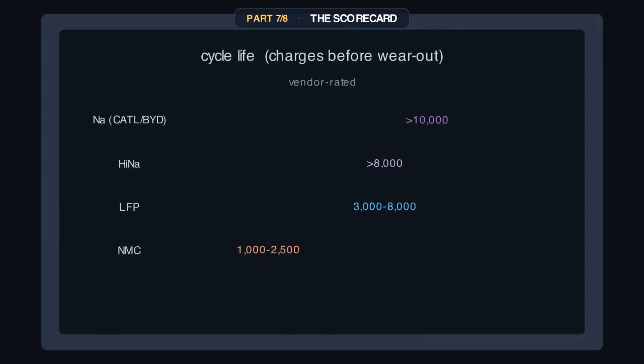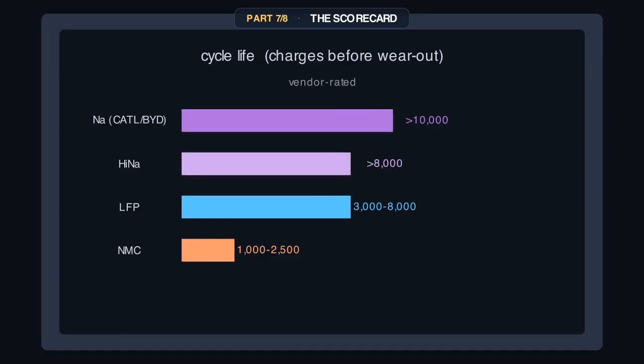Here the challenger lands a real punch: cycle life. Manufacturers rate the best sodium cells above 10,000 charges. CATL and BYD claim past 10,000. HiNa past 8,000. I'll attribute those to the vendors, but even conservatively, that matches or beats LFP's 3 to 8,000 and crushes NMC's 1,000 to 2,500. For something that sits on a grid cycling every day for 20 years, this round matters far more than raw range. And now the round that finally cashes in our paradox, the cold.